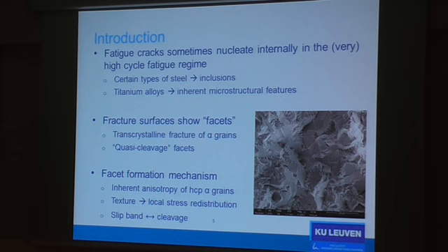In literature, you find that these facets are sometimes called quasi-cleavage facets, and this term immediately tells us that it's a bit ambiguous, because there is some discussion on how these facets are formed, how the crack formation occurs. There's a large group of publications that says that there is a slip-induced formation, but there are also publications that claim that there is a cleavage fracture, so micro-cleavage of the grains. My talk is exactly to see which mechanism occurs, and we will try to find this out.